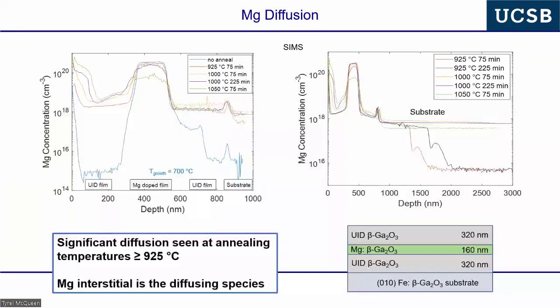And if we anneal it at temperatures that might be used in process temperatures, we actually see the magnesium move. The magnesium's really moving. These might be the process temperatures used if there was a subsequent implant in the material to activate the implant. So these temperatures are not irrelevant for gallium oxide devices, because a lot of folks who come out of other device technologies can't resist the temptation to do the worst thing to a semiconductor, which is implant it and then anneal. And so the magnesium actually moves.